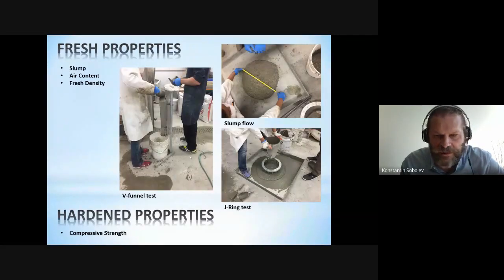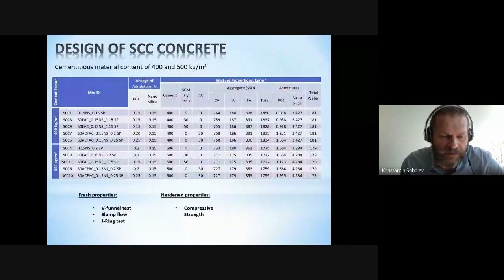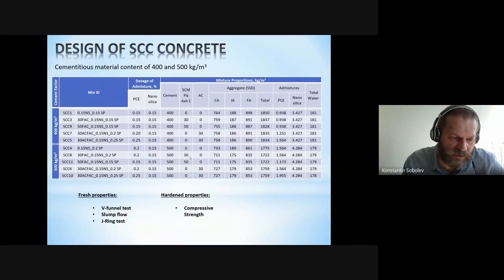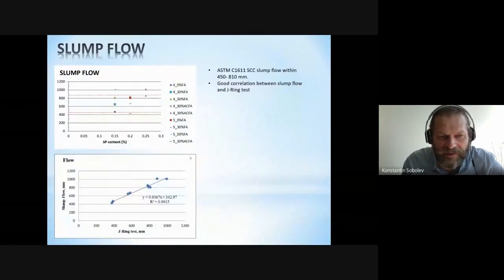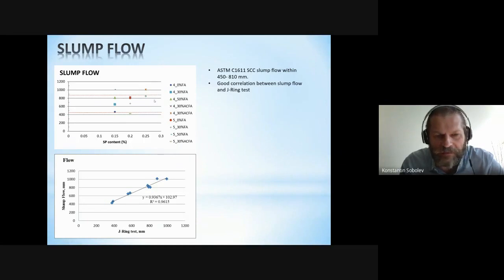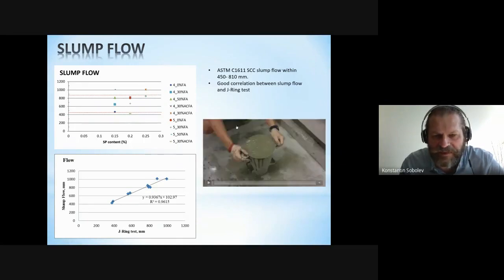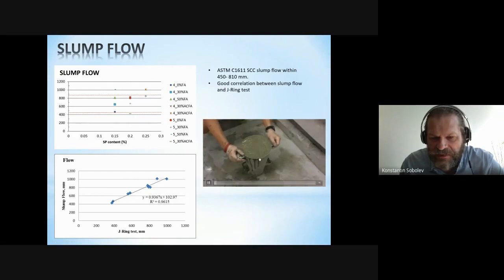Obviously, application of this material in self-consolidating concrete was beneficial. So we ran an experimental program with two series with 400 kilograms per cubic meter and 500 kilograms per cubic meter of cementitious materials. And we had excellent flow properties. We measured that, and this is the range for slump flow, and we had excellent response.